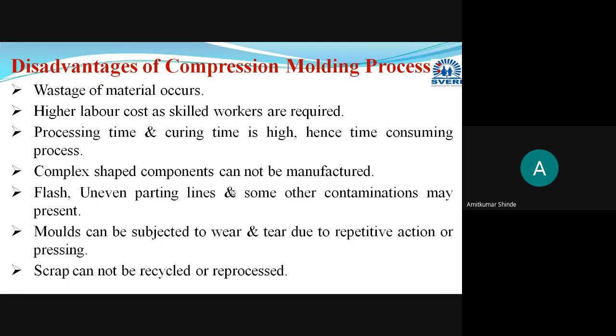And then the third disadvantage is that processing time and curing time are on the higher side. If you compare it with the injection molding process or other processes, it requires more time. Curing time is 1 minute to 5 minutes. Due to that curing time, total processing time will be more, or cycle time will be more.